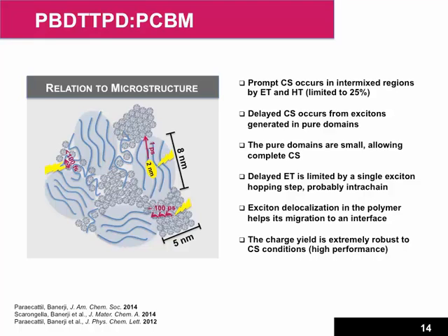And so probably what is happening is that this exciton is quite delocalized, about 2 nanometers, and it can reach a fullerene by a single hopping step along the same polymer chain. This explains why this process can be very fast.